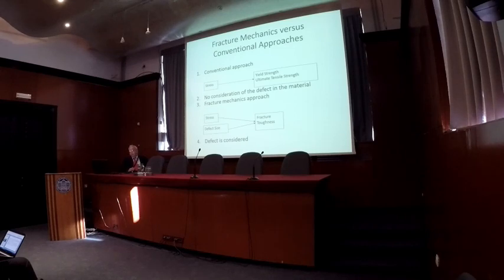And here is a little bit of schematic on the difference between fracture mechanics and conventional approaches. When I teach undergraduate, we do a kind of one parameter failure analysis, that is stress, sometimes strain, but mostly stress. We have stress calculations in mechanics of materials, and then we calculate the stress. And if these stresses reach yield strength or sometimes ultimate tensile strength, then a failure occurs. But this has no consideration of defects in the material. So the fracture mechanics approach, shown below, takes two parameters, the stress and the defect size, and puts them together into a concept that we call fracture toughness. So the defect is a very important thing that's considered in the fracture mechanics approach that conventional approaches wouldn't do. So number one in fracture mechanics importance is considering the defect.